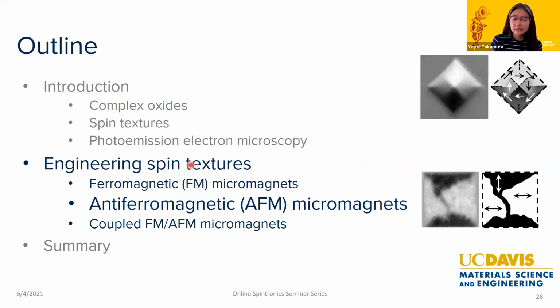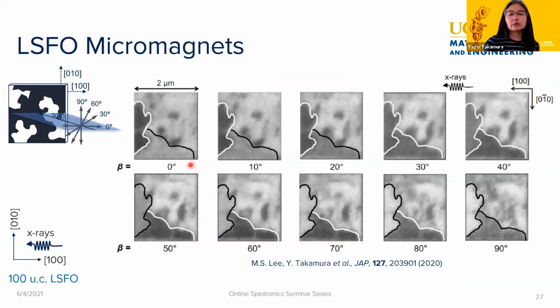Okay, so that was when we had our ferromagnetic materials, and then I want to show you what happens when we deal with the antiferromagnetic materials. And antiferromagnetic materials are always interesting because typically there's no magnetostatic energy. So one usually thinks, if I pattern an antiferromagnetic material, it shouldn't matter how I pattern it, right? But I'll show you that we actually do see some shape anisotropy effects.